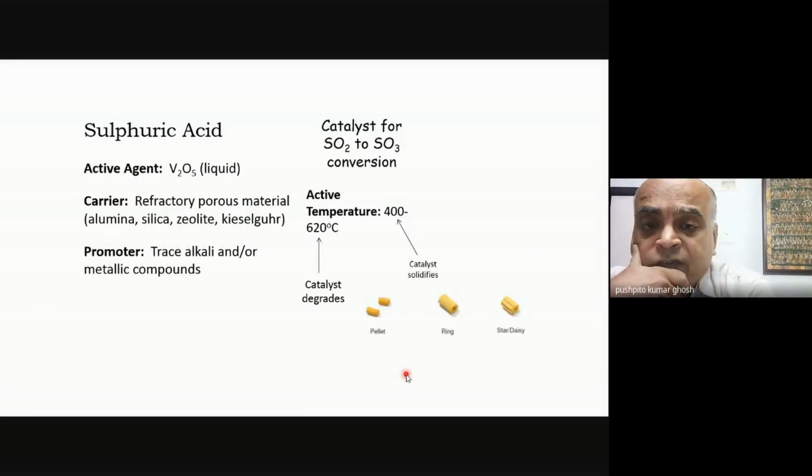What happens is that, and this is what BASF presumably would have said, that look, if at 400 degrees Celsius or thereabouts I am getting more or less 100% conversion, then let the lowest temperature at which I am going to operate be around that temperature, around 400, 450 degrees centigrade.